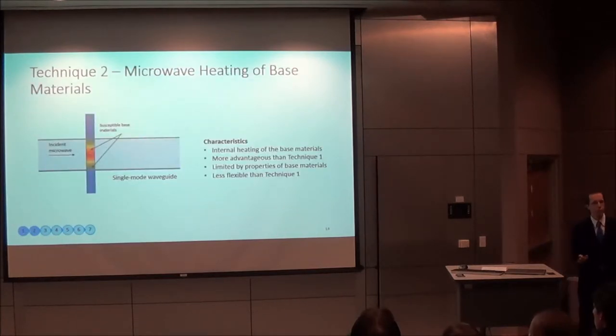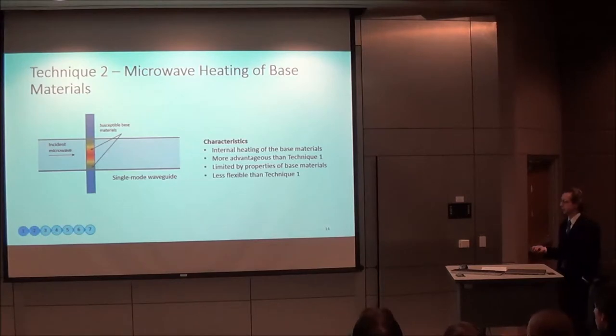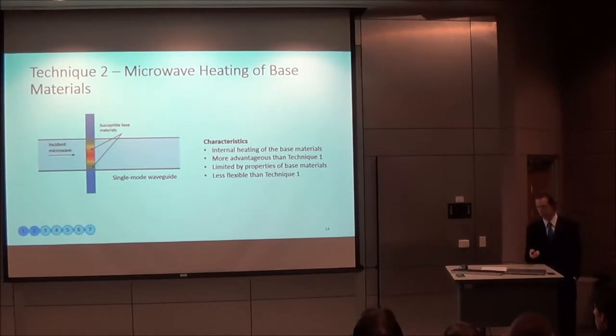Technique two is where the base materials will be directly heated by the microwave. Oftentimes this is done in a single mode waveguide, not in all cases, but oftentimes. And you may have two base materials extending into the waveguide, and where they meet is where the energy is focused, and the base materials generate heat. This is an example of internal heating, so it is more advantageous than the first technique. But it's limited by the base material properties, and so it's less flexible. We can't use as many different types of materials, as many different joint configurations, shapes, sizes, etc.